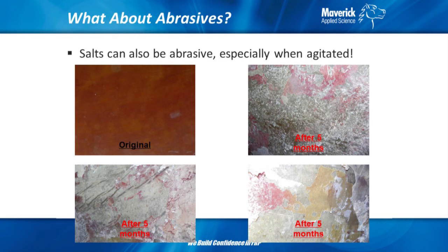What may not be known is salt can also be abrasive, especially when agitated. We found this out very clearly not too long ago, where this was, it's hard to see, but this was around the original look of the liner. And after 5 months in operation, a lot of wearing of the veil. Now, I will say there could be some manufacturing issues that led to this, but I believe the resin was only selected because of the chemical service, not considering that there is an agitator in there. I mean, after only 5 months, this is very, very substantial, very, very concerning wear.